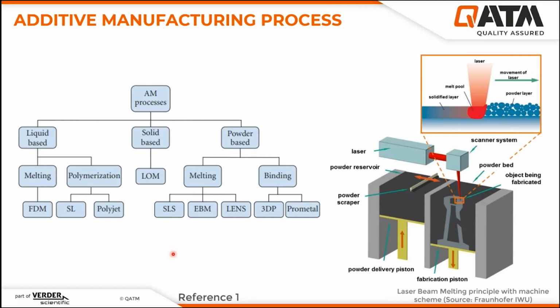On the left-hand side, you can see the different additive manufacturing processes. It can be liquid-based, solid-based, or powder-based. In the liquid-based, we can have melting or polymerization, and in the powder-based we can also have melting and binding. You have seen the names of these different processes, and you may also be familiar with them. On the right-hand side is an example of the additive manufacturing process. As you can see, we have the powder layer, and when the laser goes through the powder layer, we have the melt pool, and behind the laser, we have the solidified layer.